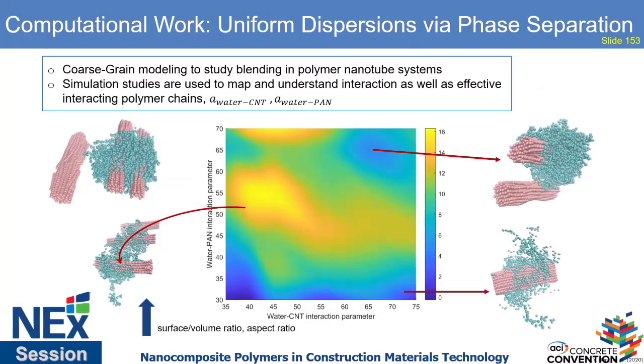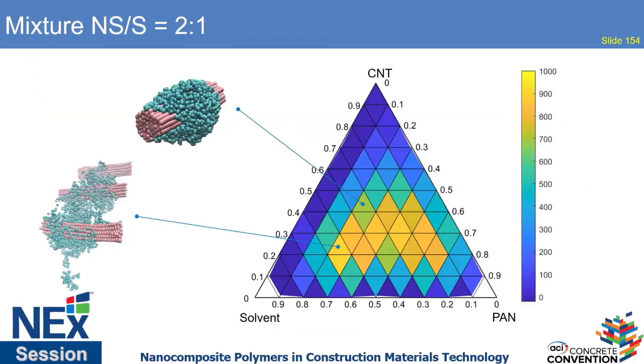We've studied this computationally as well. So again, my lab is primarily experimental, but in the computational sense, we wanted to understand this because when you're working with nanotubes, everything is black. You can't see anything, and the microscopes don't always get everything. So by changing the solvent-non-solvent interaction, we can change the way the polymer in the green here is interacting with the various bundles. And we can create phase diagrams that actually help us to tune our processing, where in some cases, different windows of nanotubes, solvent and non-solvent, as well as the polymer, allow us to have a better interaction between the polymer and the nanotube bundle, or less better interaction.